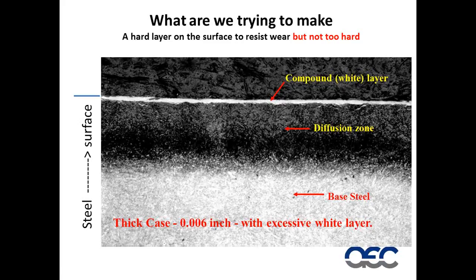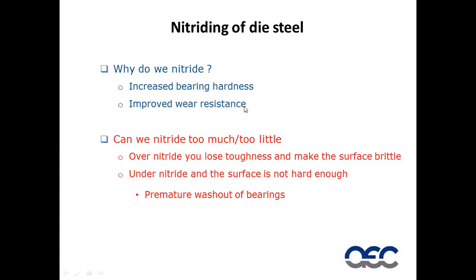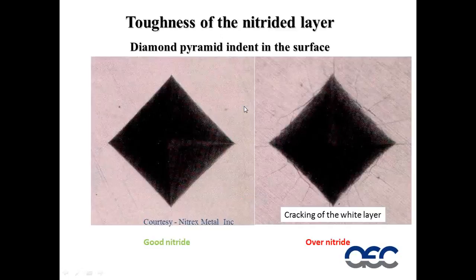The compound or white layer is caused by being too aggressive in our nitriding, too hot, too high a nitriding potential, and we make a layer which is more like glass than it is hardened steel. And this can be a problem to us, and I'll cover this a little bit in a moment. If we take a close look,